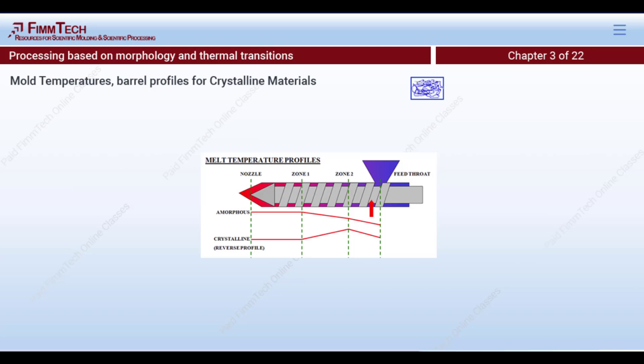In the feed section you just need to give enough heat for the plastic to start softening. However, with crystalline materials, the crystallites require a lot of energy to melt — they do not soften easily. So you give a boost of energy to soften the crystallites, and once they soften, the whole plastic pellet becomes soft, achieving its purpose in the feed zone.